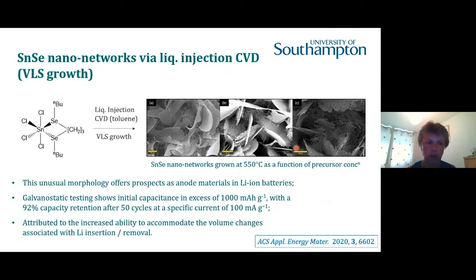And SnSe, tin monoselenide, is an interesting material, like many of the chalcogenides, for new anode materials in battery applications. And we've done some preliminary work, and this has been very much in collaboration with Cork, looking at these for intercalation of lithium ions for lithium-ion batteries. And what we find is, again, it's fairly early days with this work, and we've obviously got more work to do. But because we've got this very open structure, we retain very high capacities after multiple cycles. So after about 50 cycles, a bulk material or a film would be decaying down to maybe 40% capacity. We're seeing retention of high capacities because of the open structure, because as the lithium goes in and out